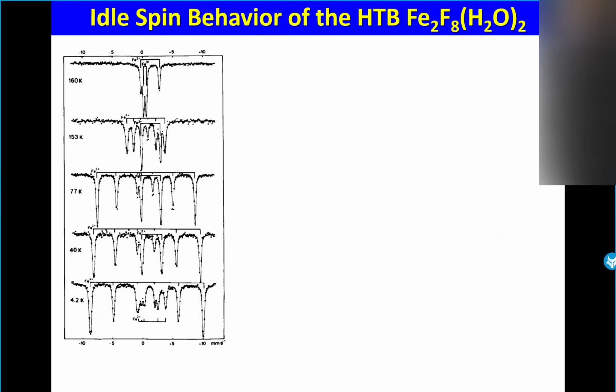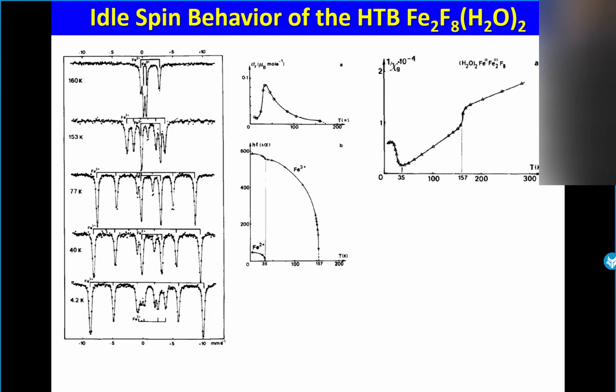So, at room temperature, you have two doublets. It's clear that we have one doublet typical of iron 2 and one doublet typical of iron 3, according to the value of isomer shift. You decrease the temperature. What you can see is the doublet of iron 2 is still present, and the doublet of iron 3 splits into a sextet. On this sextet, the lines were increasing, which means the hyperfine field increases when the temperature decreases. But below 20K, you can see that the surviving doublet, attributed to iron 2, becomes a sextet. It splits also.